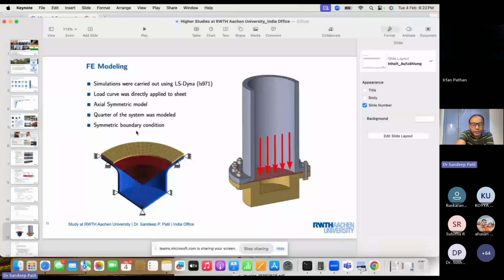So what we did, we just considered a quarter of the system. We modeled it, and we put in axisymmetric boundary conditions. You can see here, this is a die, this is a die holder, and this is the sample blank, which is the red color. We applied the pressure on the portion which is open to the gas detonation. So this is what we did.